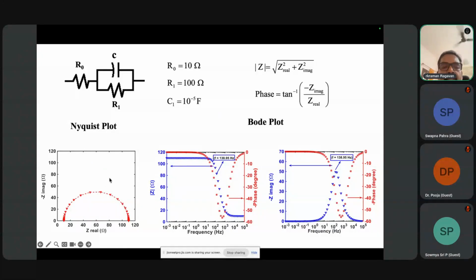Okay. Now we can also plot them in another way, because in this plot we cannot see the frequency information. If you look at the publications, people generally mention select frequencies, frequency here, frequency here, frequency here. So we can also plot frequency versus the total impedance. You can see the total impedance at high frequency depends only on R0. So at high frequency, you have a value of about 10 ohm. But when you go to very low frequency, it is 110 ohm. So at some frequency, the characteristic frequency, omega RC, you will see there is a sudden inflection and then it goes like that.